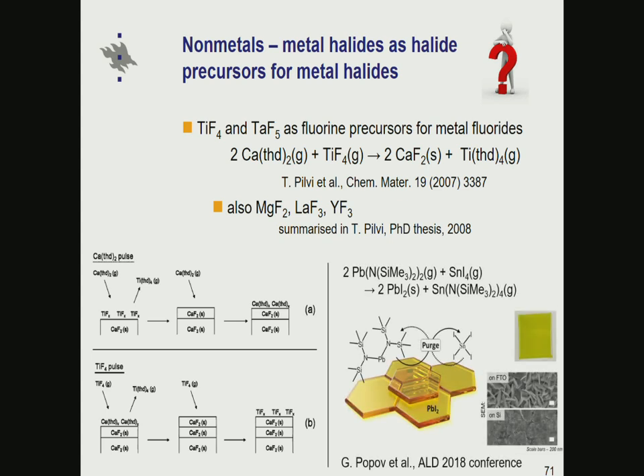And just this year, Georgi Popov gave a presentation at the ALD 2018 conference where we did the same with iodide. So now tin tetraiodide is the volatile metal halide compound, and when it's reacting with this lead compound, it produces lead iodide. But only at very low temperatures, because this lead iodide, this metal halide, is also volatile. It has been earlier used as an ALD precursor, but working below 100 centigrade, so one could deposit pretty nice lead iodide film through this exchange reaction.